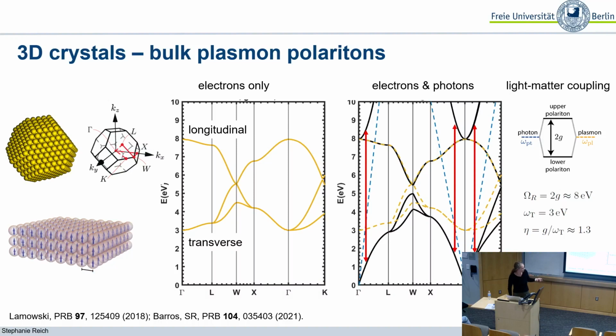The frequency of this transverse plasmon is roughly 3 electron volts, so we neglect the small dispersion that you can see here. So if you look at the so-called reduced coupling strength, which is the ratio between g and omega T, you can see that it is larger than 1. And this is a regime of light-matter interaction called deep strong light-matter coupling. It means that if you think back to the Hamiltonian we started from, where we said we have the atom and we have the photon, and then we have a perturbation, which is the interaction, now all of a sudden this perturbation is actually stronger, larger than the two excitations we started from.